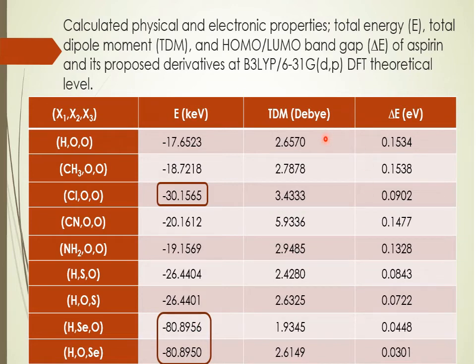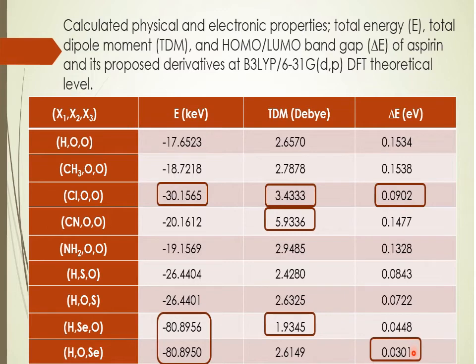Total dipole moment of aspirin is 2.6570. All the substituted groups have nearly the same reactivity except chloride and cyanide in position X1, which have higher reactivity, and selenium in position X2 has the lowest reactivity. Band gap energy of aspirin is 0.153, but chloride in X1 has a lower value and more conductivity. Also, selenium in X3 has the lowest value and higher conductivity.